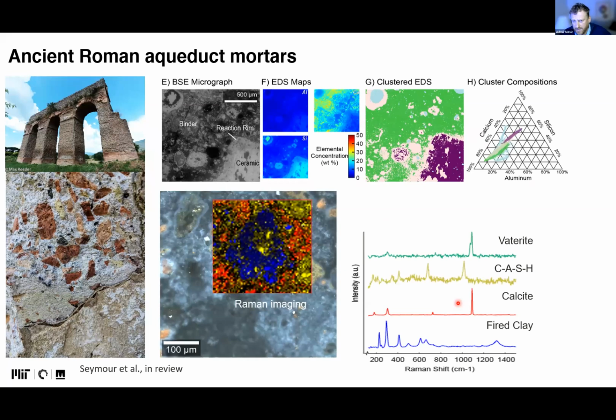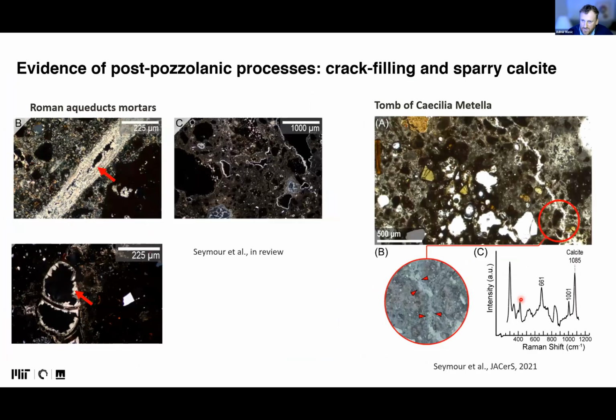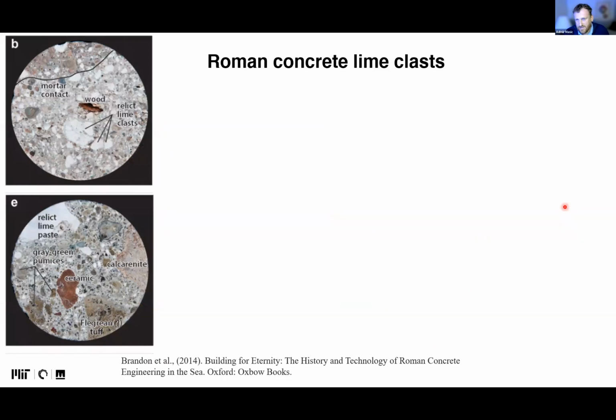Another paper that is about to be published is the same story, but now with materials that we make. So these are cocciopesto, ceramic man-made materials that were introduced when volcanic ash was scarce, or in applications for water-related infrastructure, so aqueducts, thermae, and things like that. Also in this case, we observe the same reactivity of these now anthropogenic, man-made inclusions, with very similar reactivity, CASH and calcite. What we observed also, and this is now connected with the next slides, is that there is a lot of calcite everywhere, including cracks. You see this crack here. It's filled with calcite, and that actually very nicely fits with what